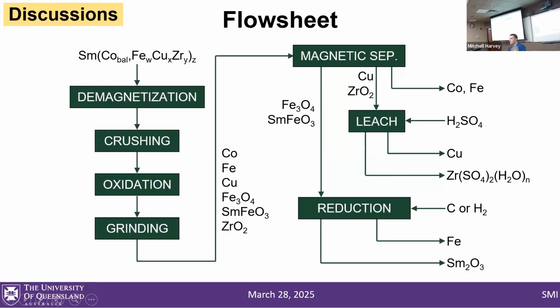Our strongly magnetic phases, cobalt and iron, are recovered as is. Our copper and zirconium oxides are our non-magnetic fraction. We then leach those with your acid of choice—in this case sulfuric acid. We can control the Eh and the pH to not dissolve the copper, but dissolve the zirconium.